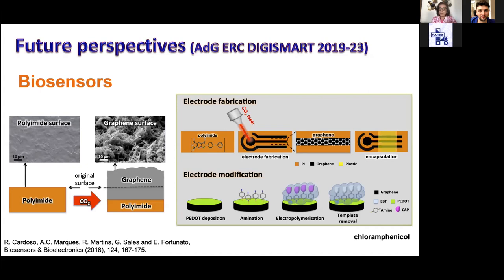This is very easy because, again, we can use the laser beam to convert the surface of the polymer or another material. We need to have carbon, and convert the surface of the material to graphene, and use this graphene, for example, in that case for a biosensor. We use this for the detection of antibiotics, and this is also flexible.